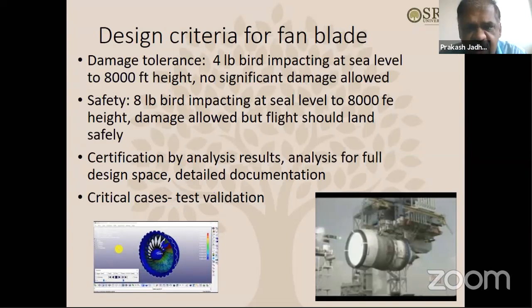So then how do you satisfy all these requirements? Of course, there is a set of analysis. There is a design space in the sense that for all the loading requirements, like 4 pound bird, 6 pound bird, 8 pound bird, at different velocities, at the ground level, at 3,000 feet level, at 8,000 feet level. Also the relative speed, in the sense that the aircraft is cruising at certain speed, so that is basically the speed of the bird. And also the fan is rotating at 3,000 RPM. So there's a linear speed and there's also rotational speed. So the relative speed becomes too high. Because if you do the calculation of this linear speed plus the rotational speed of the fan blade, ultimately the relative speed that you arrive at is very high.